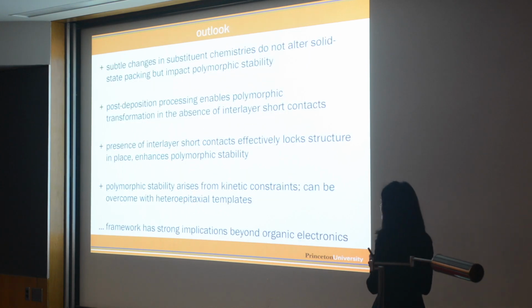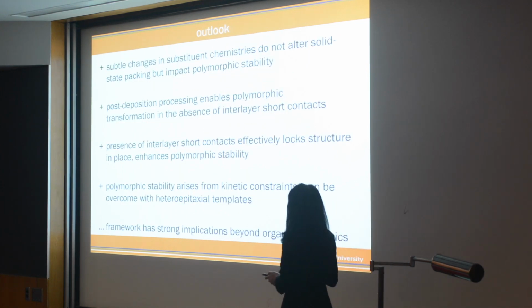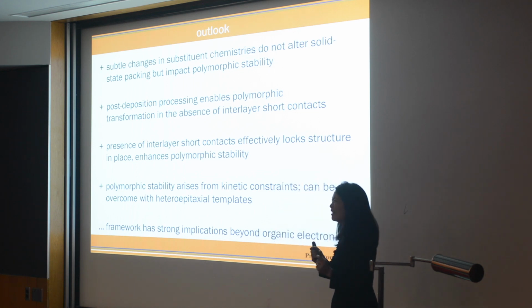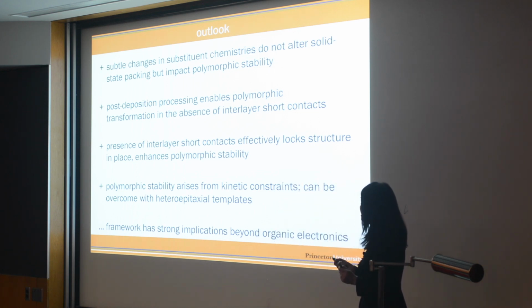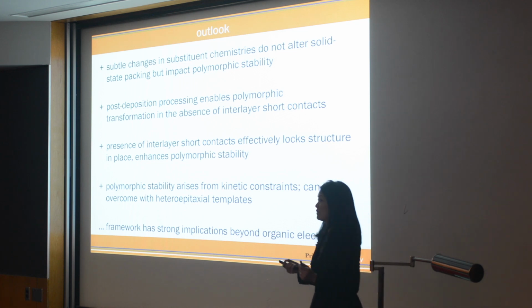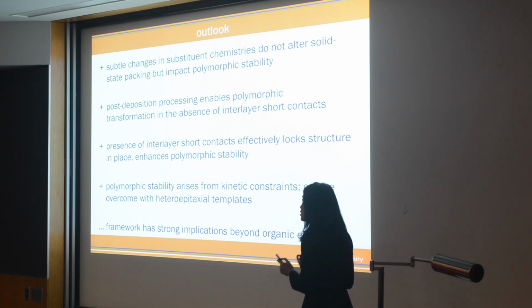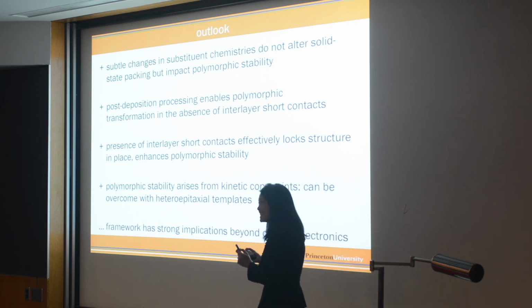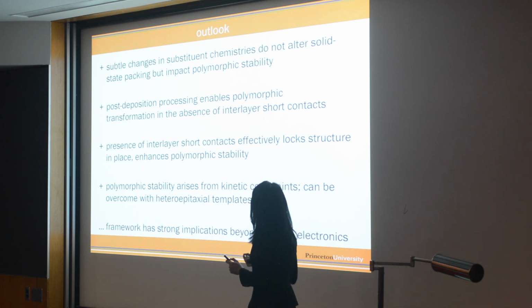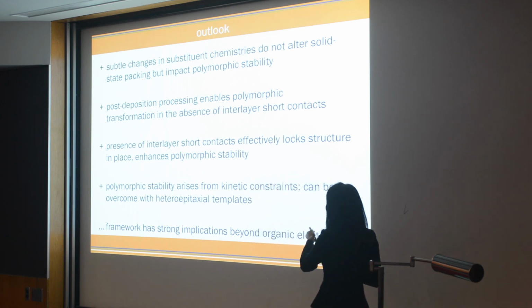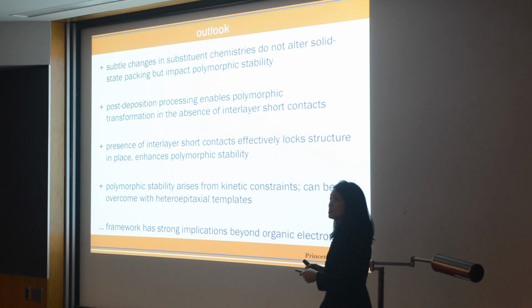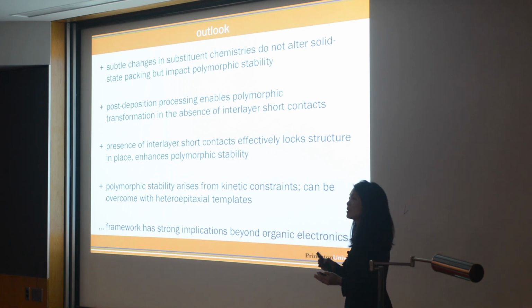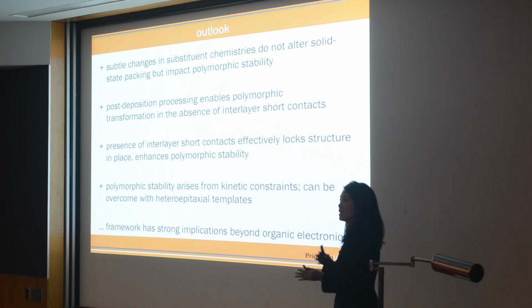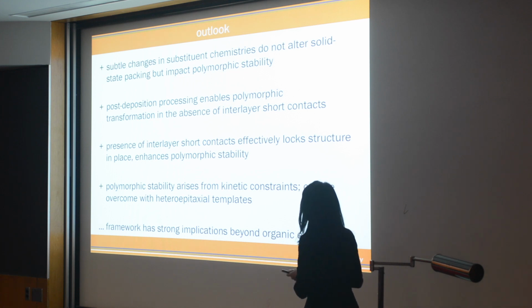So where does that leave us? A couple of important points. These subtle changes in substituent chemistry, they don't really alter the solid-state packing, but they impact polymorphic stability. And this polymorphic stability that I'm talking about is a kinetic stability. Okay? So in the absence of these interlayer short contacts, you can use post-deposition processing to convert between these polymorphs. And you can go back and forth, back and forth, back and forth.